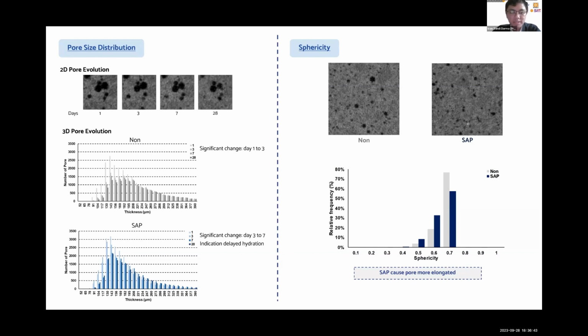in SAP specimens, significant change occurs in day 3 to day 7. This indicates the delayed hydration from some water still inside the superabsorbent polymer. We can also observe sphericity of the specimen. SAP causes more elongated pores following the SAP structure.